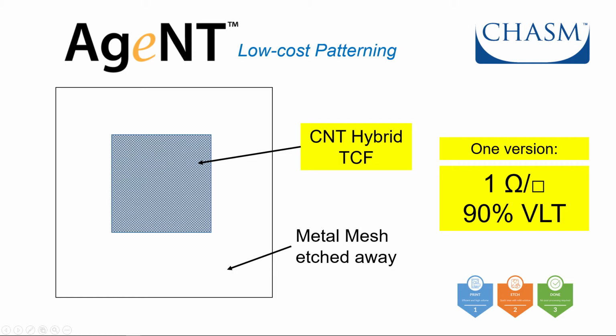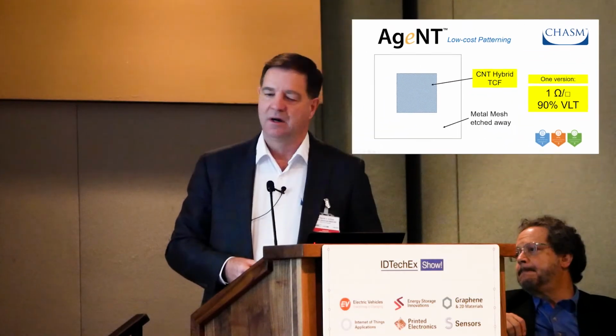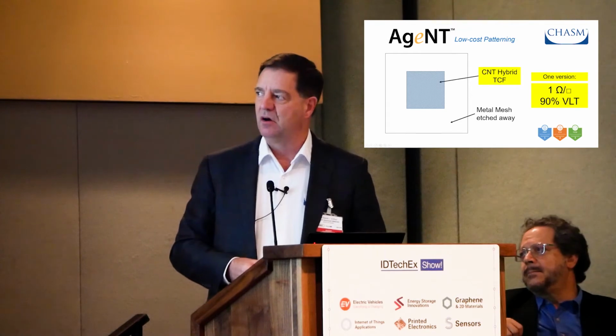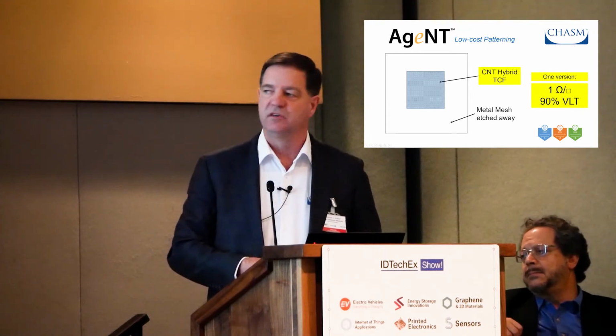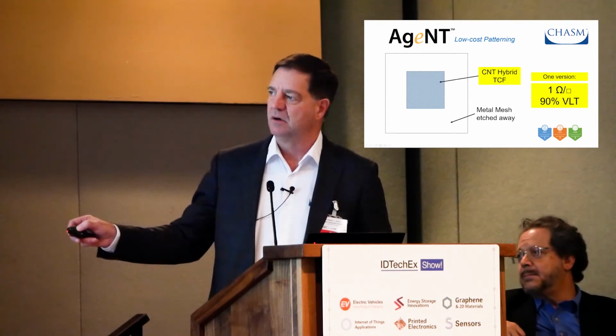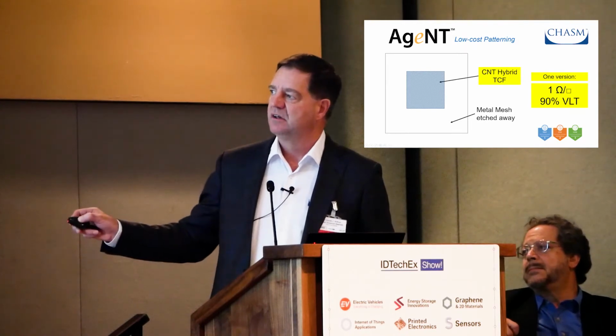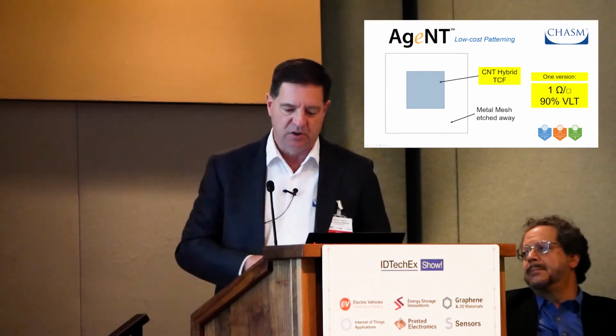This version, we developed the metal mesh version because applications, specifically transparent antenna applications, do require a lower ohm per square. So that was not practical to achieve that ohm per square with current generations of silver nanowire film. So we developed a metal mesh version of AgeNT, 1 ohm per square and 90% visible light transmittance.